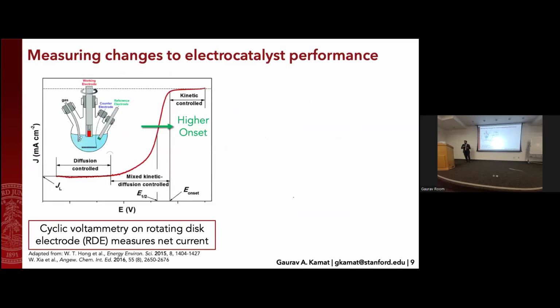So given all of this background, how do we actually measure an electrocatalyst performance? So this here is a rotating disc electrode setup. It's one of the most common electrochemical setups for measuring performance. Your electrode is immersed in liquid and it's spun around. You have a counter electrode that balances the reaction, and a reference electrode that provides you a stable potential so that you know actually what potential things are happening at.